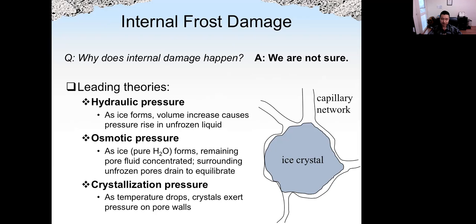And the third possible theory is called crystallization pressure. That is when the temperature drops, the crystals, such as ice, will exert pressure on the wall of the pores. So that pressure from the crystallization may also cause the cement paste to crack. So these are three possible reasons we have internal frost damage.